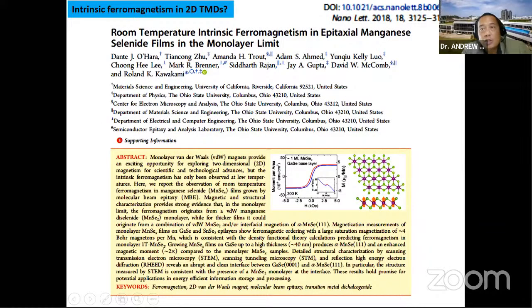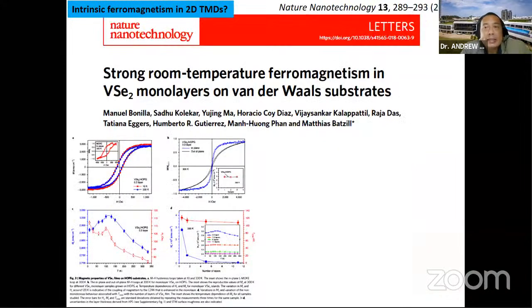And so this work in 2018 by the Riverside group, Kawakami's group, showed that manganese selenide 2D films are ferromagnetic, but you can see the ferromagnetism is quite small, the hysteresis, and of course they use standard magnetism measurements to measure them, and I'll comment on that. And another paper in Nature Nanotechnology in 2018 by the Florida group, University of South Florida, Batzel group, showed that vanadium diselenide monolayers showed strong room temperature ferromagnetism. That's why this work attracted a lot of attention, because it's room temperature. And that has, of course, as I mentioned earlier, a lot of applications. So you see the raw data here showing the hysteresis and so on.